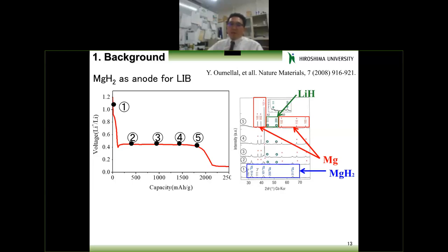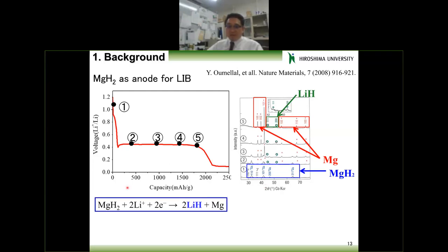But if we focus on magnesium hydride, at about 0.5 volt there is one quite clear plateau, and another plateau is here. This first plateau corresponds to the magnesium hydride reacting with lithium. Then lithium hydride was generated, and magnesium was also generated as a byproduct.